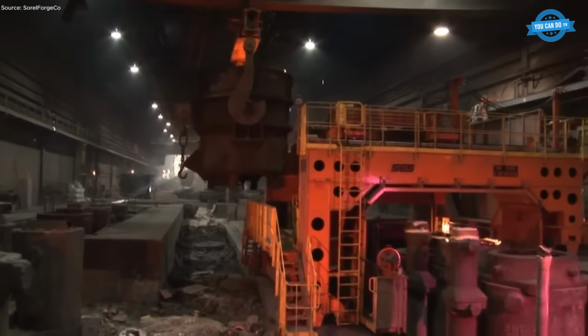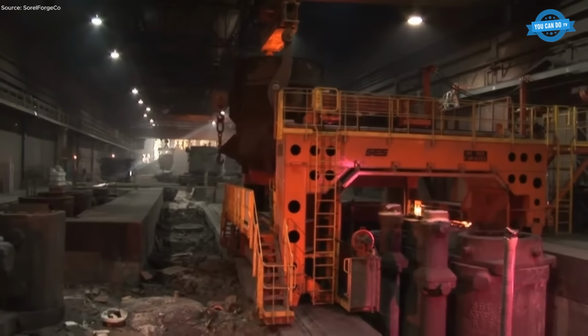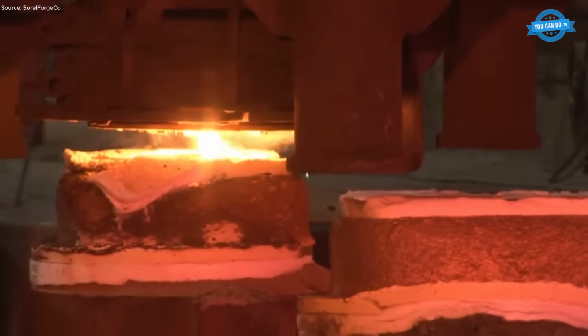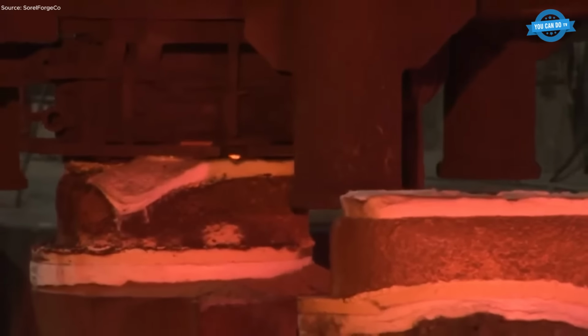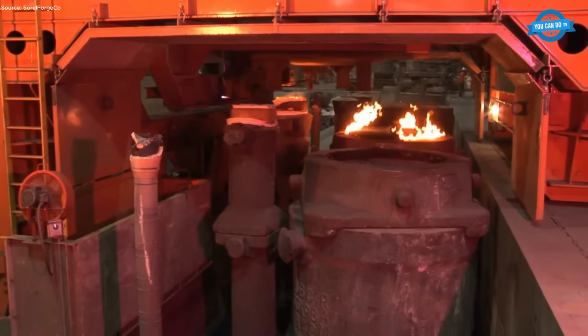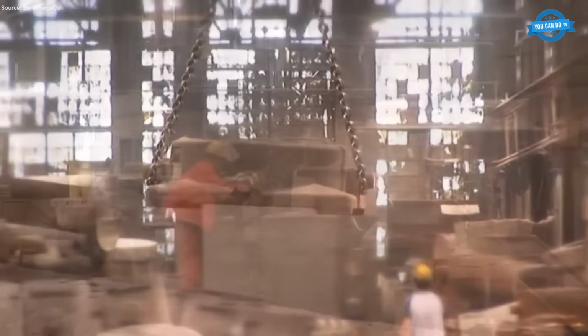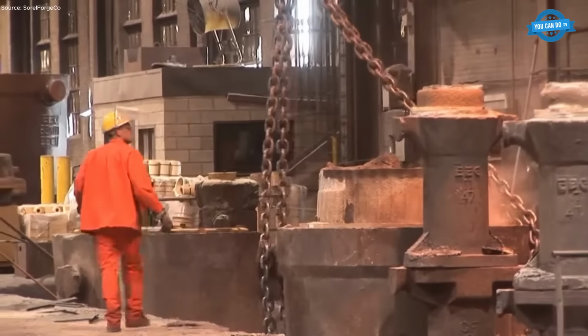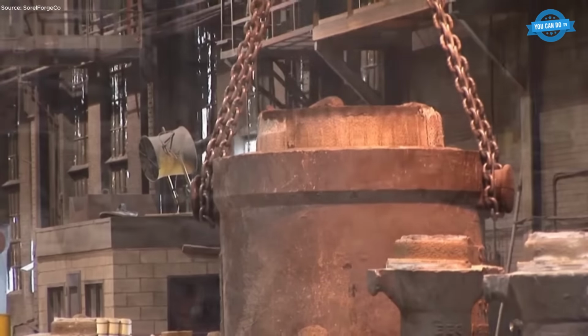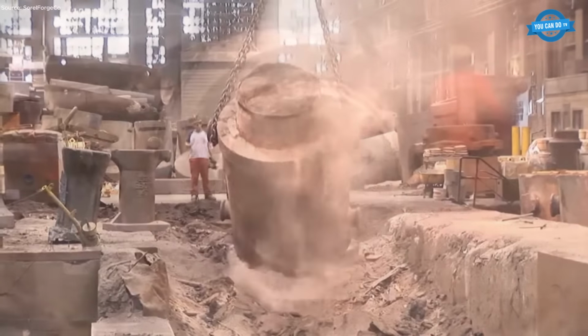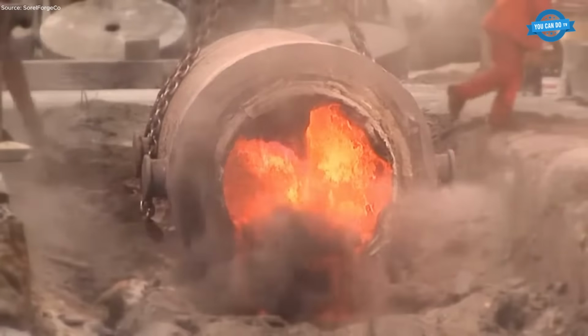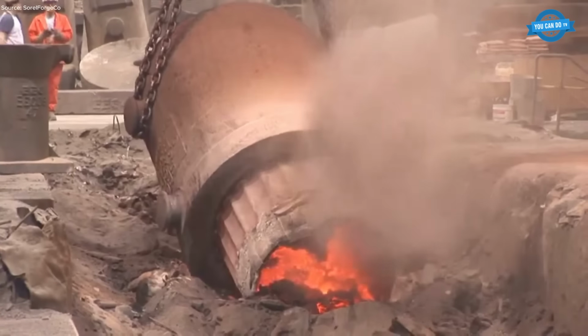Argon gas is gently bubbled through the liquid metal, promoting the flotation of non-metallic inclusions toward the surface. These impurities are captured by a layer of synthetic slag, which also protects the steel from reoxidation. Oxygen levels are carefully controlled to ensure high cleanliness and quality. After degassing, the refined molten steel is ready for casting.